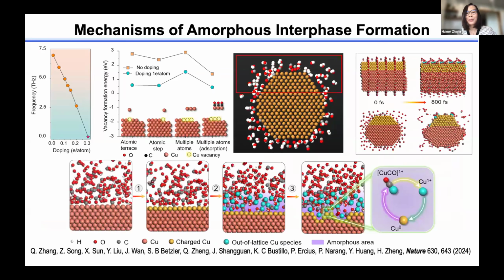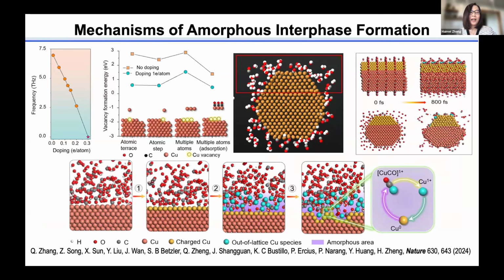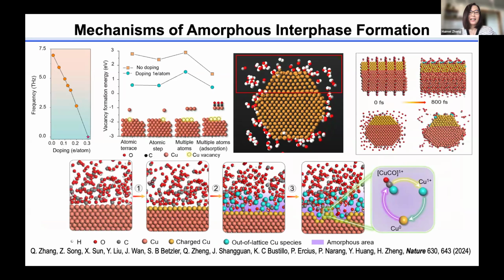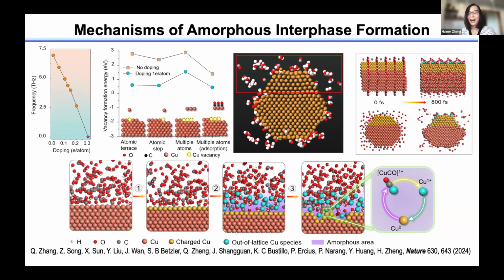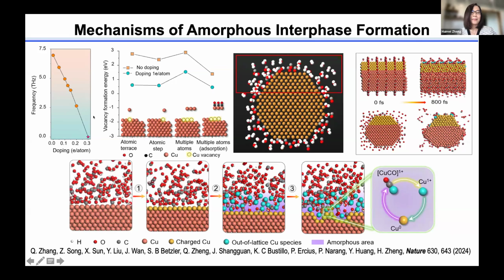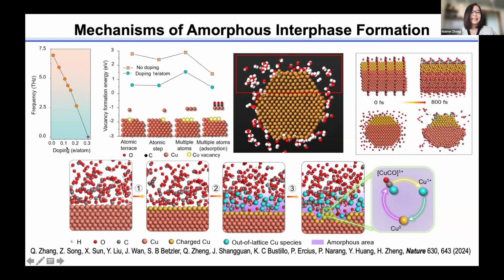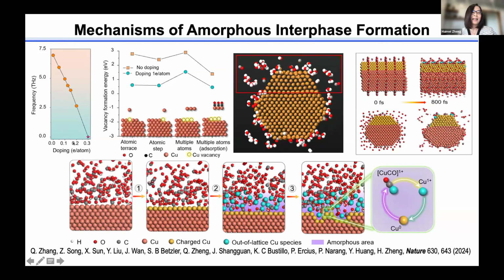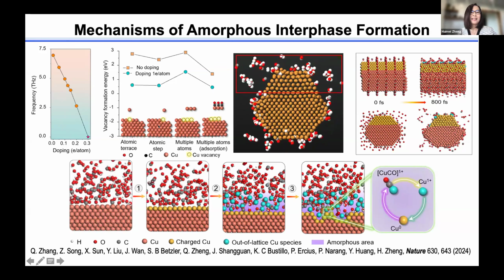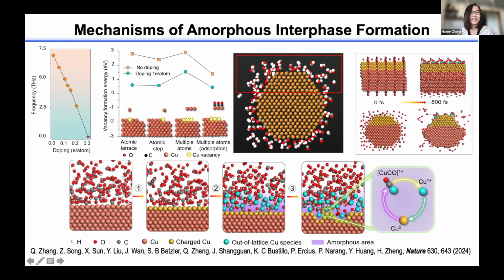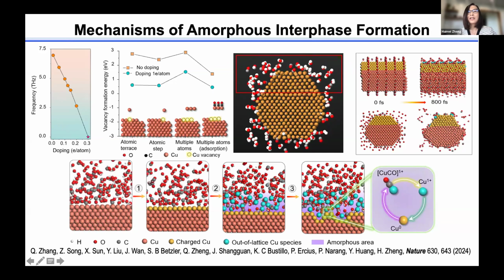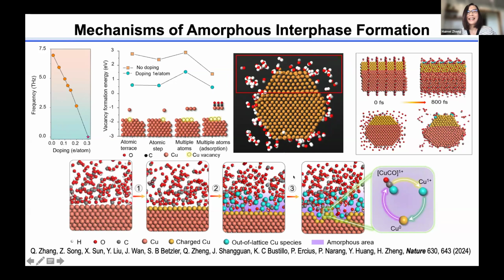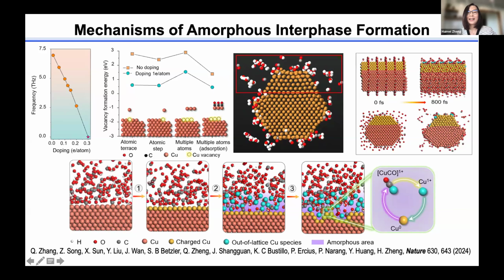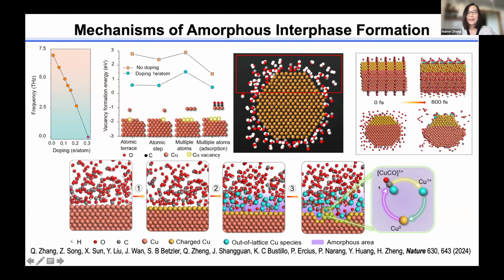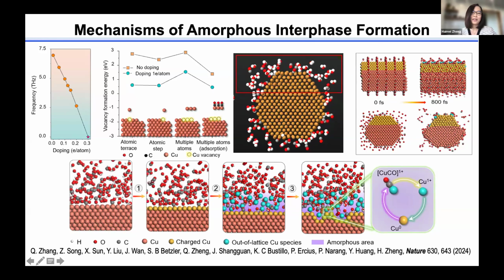And we collaborated with a theorist, Dr. Zhigang Song, working with Professor Prineha Narang at Harvard at that time. Zhigang did a systematic study, and this shows a phonon calculation that really shows that with electron doping, the surface can be activated. With this activation, the electron-doped surface can be more active than without electron doping. Using MD simulation, he replicates this amorphous formation, showing the intermediate copper ion and copper zero dynamic transformation.